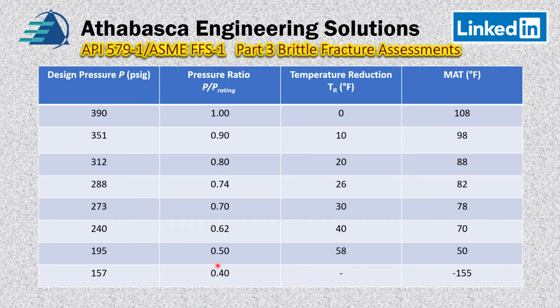But something interesting happens. We remember our 0.4 curve, which we determined earlier. Well, that tells us that we have to use minus 155 degrees Fahrenheit. Even if we have a stress ratio of 0.1, we still have to use that factor. Those are the rules.